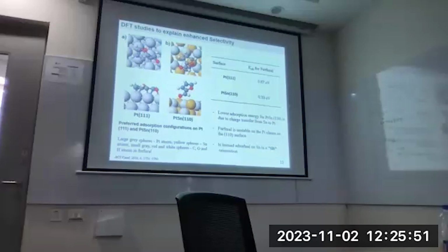But when I did the chemisorption experimentally, when I tried to put the hydrogen and see how much of it is adsorbing on the surface, because I want to know how much platinum is on the surface, I was not able to get any chemisorption using hydrogen. So with DFT, I think we have to give them the data first. What I did for this particular reaction was the kinetics. I got the activation energy, I got everything, and then I gave them that data, and they predicted this is what's happening. So it comes after the fact, even though it should come before and tell me how to do my experiment. But in my work, at least, it always comes after I do the experiment.